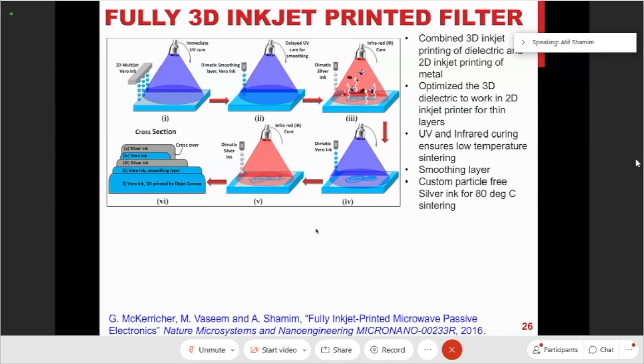And talking about when Benjamin and I started back in 2011 or 12, we've come a long way. We now have fully printed processes, multiple layer processes. We started with oven sintering, but now we use a lot of different kinds of sintering mechanisms, whether UV or flash or infrared, and we can now hack. We actually hacked ink. This is the work of one of my Canadian students, Garrett. We could hack ink from 3D printers into 2D printers, and 2D printed ink into 3D printers. Sometimes we need to make thicker layers, sometimes thinner layers. We can do crossovers, we can do vias. We've arranged the whole multi-layer process.